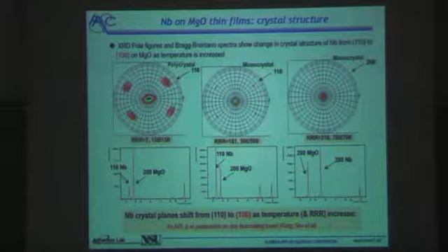I should also remind you that the field at which these images are taken is 12 by 12 millimeters. We're not looking at some tiny dot on this film. It's a global measurement, unlike EBSD, which is a tiny spot which we then raster back and forth and which looks only at the surface. These are copper K alpha X-rays. They're penetrating this 1 micron film. When you get to this intermediate condition, you obviously see the polycrystalline behavior is becoming more like a monocrystal. You can see that in the sharpness of these Bragg-Brentano spectra peaks and their intensity.